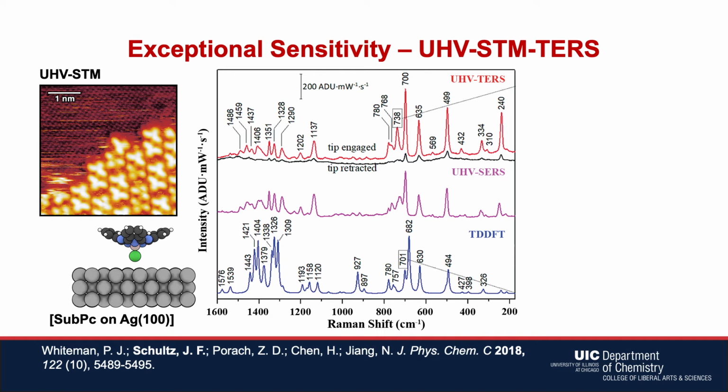This first project shown here highlights the ability to use this instrument to combine both techniques. As shown in the top left, it was possible to obtain high-resolution STM images of self-assembled boron subchlorophthalocyanine (SubPc) molecules with atomic resolution of the adjacent Ag(100) surface.